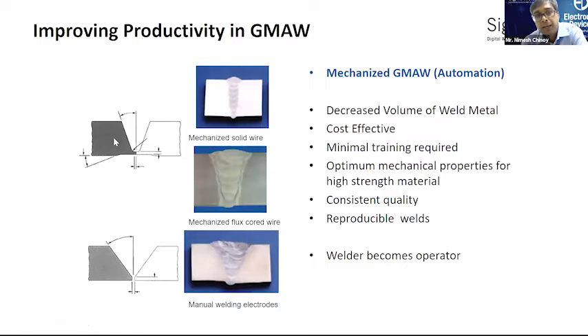Now, as we were sharing before, this is what is meant by a traditional V-groove preparation, and this is what is meant by a narrow or mechanized groove preparation. You can see there is a good change in the V. This is what the included angle sir was talking about. It shows that you will be depositing a lesser amount of material, thereby having quicker productivity. So the advantage of going mechanized is you decrease the volume of weld metal put.